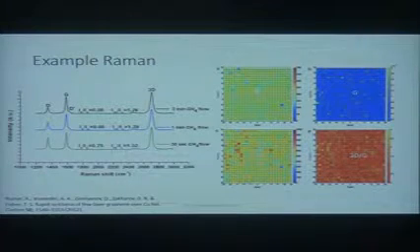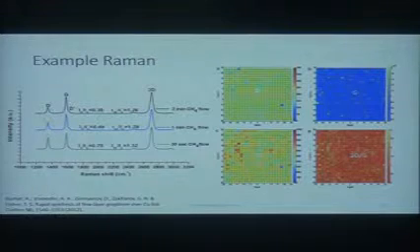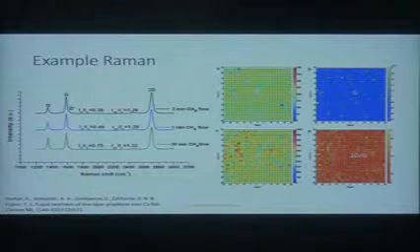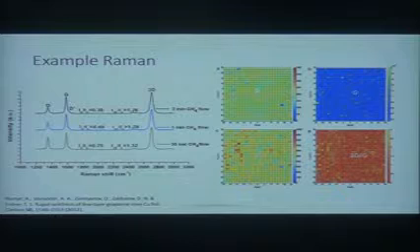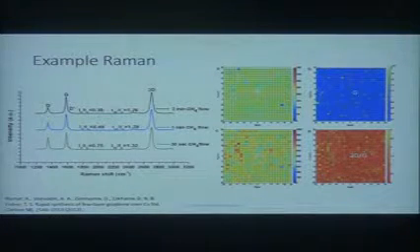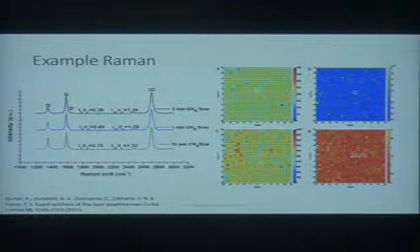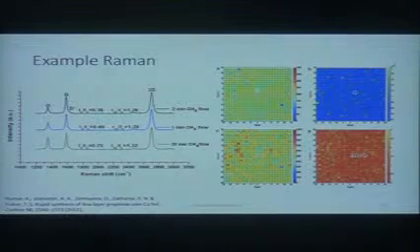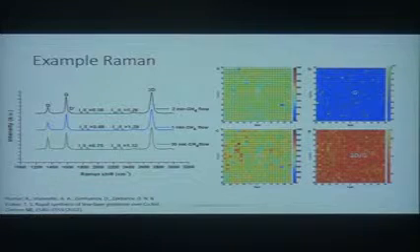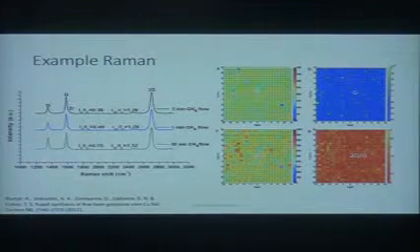solid state. So here again, I tried to use the same paper as much as possible. This is again that paper on graphene, just to show you that all of these techniques, most of what I'm showing today came from one paper. We had to go through the laboratory and do all these methods in order to put it into the paper. Here's the Raman shift. This is of the graphitic material, and what you see is you have a G peak. That's what we look for if we want to have graphene or graphitic type material.